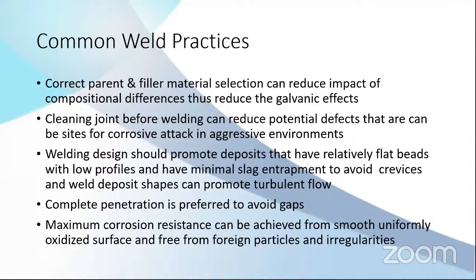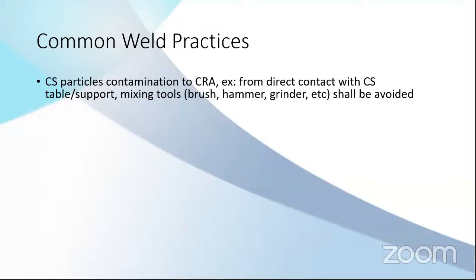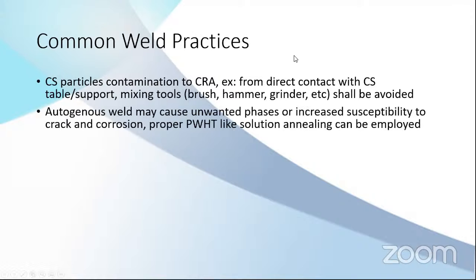And this is for the surface treatment. Maximum corrosion resistance can be achieved from a smooth surface, no heat tints, no foreign particles, no irregularities, and a pickled surface. For corrosion resistant material, try to avoid contamination, and avoid contact with carbon steel. Sometimes you put the stainless steel pipe on a carbon steel table, which is bad because it contaminates the stainless steel. Or you use the same hammer for slag removal, it can contaminate the stainless steel.